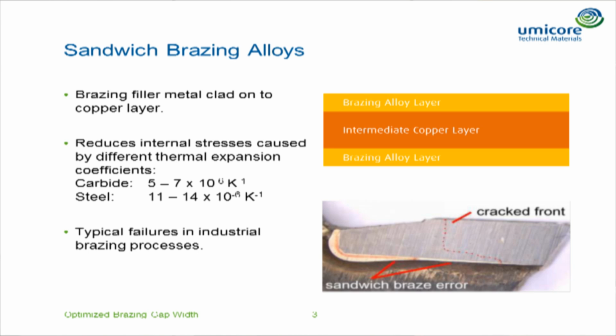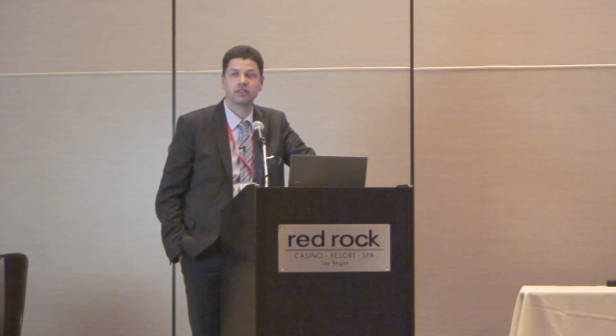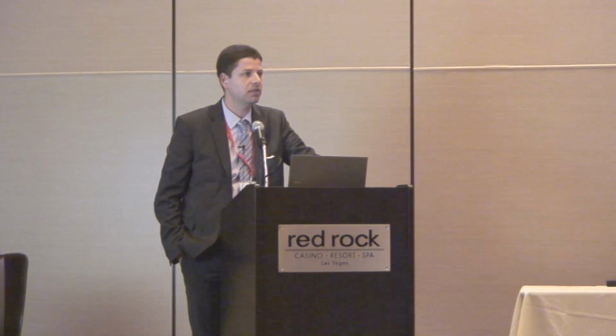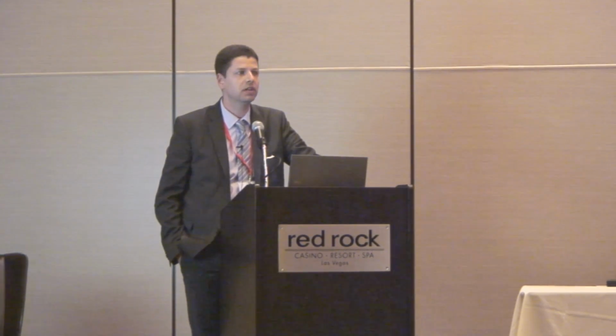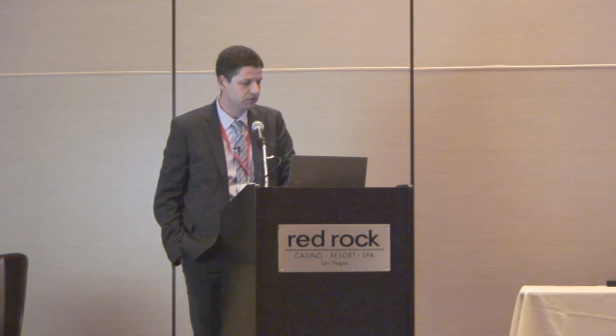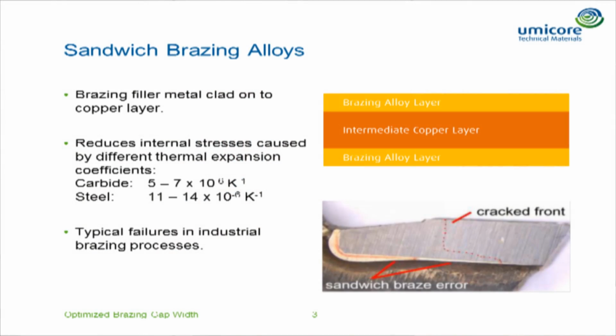What is the reason for using these special sandwich brazing alloys? The reason is the different thermal expansion coefficient of cemented carbide and steel. This does not have any effect during brazing, but after brazing, when the part is cooling down, this can result in stresses. The cemented carbide tips are a brittle material, and they don't like tensile stresses. This can lead to failures, and the job of this copper layer in between, because it's very ductile, is to take over these stresses and protect the tip from cracking.